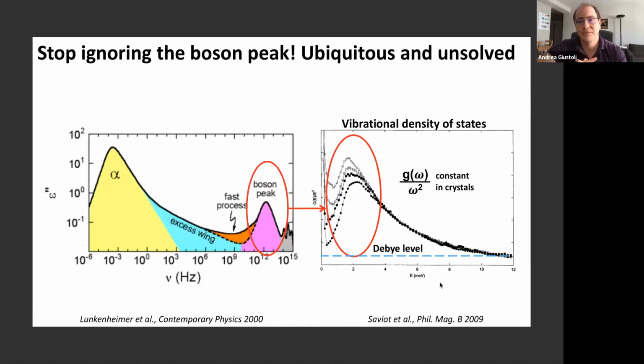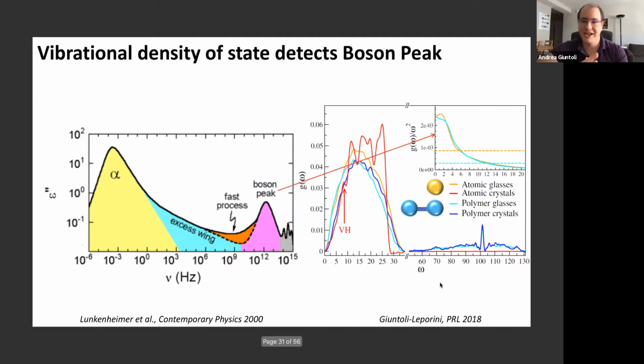But for most glass formers, what you'll see is a peak in this range, which to this day is not fully understood. And we played with this a little bit. And in particular, what we simulated were four different systems. So atomic glasses, atomic crystals, polymer glasses, and polymer crystals. So we have these four different combinations of atoms, polymers, glasses, and crystals.